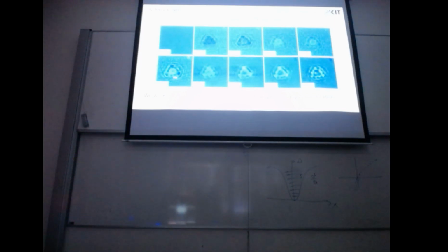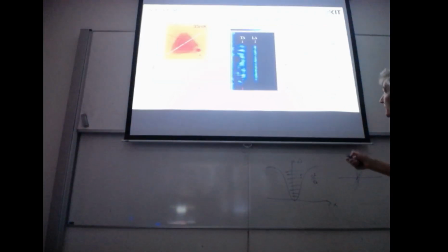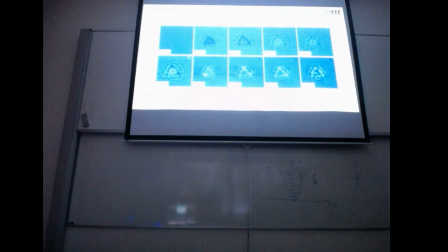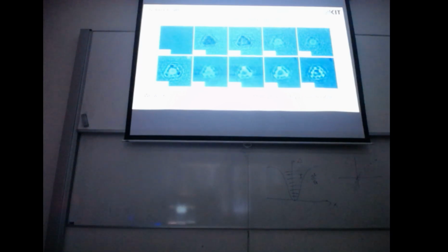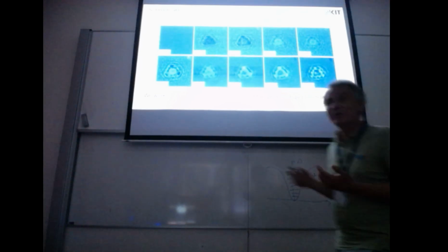And once I go to the transversal phonons, the signal actually explodes. This is actually very strong. And we can see even something like a dispersion. So what we believe is that this is the joint density of states of the phonons, standing phonon modes. And we map here the phonons. So this is the spatial wave function of the phonon. And you can Fourier transform this, and then you get the dispersion of the phonons. So we can do something like neutron scattering on the local scale with a super high resolution.